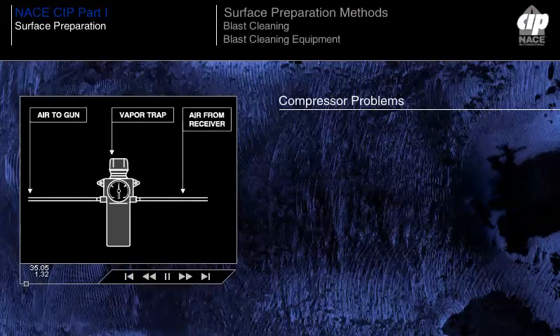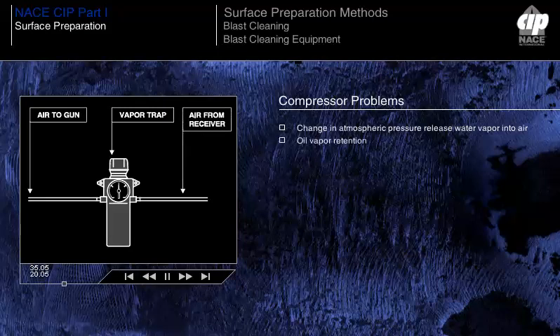The production of compressed air gives two problems to the surface preparation process. These are: any change in atmospheric pressure may result in the release of water vapor from the air. Because compressed air in the receiver is stored by pressurizing an oil reservoir, there is a possibility of oil vapor being retained by the air as it is released. Both of these factors require that adequate vapor traps are fitted to blast cleaning equipment in order to remove the contaminating oil and water.